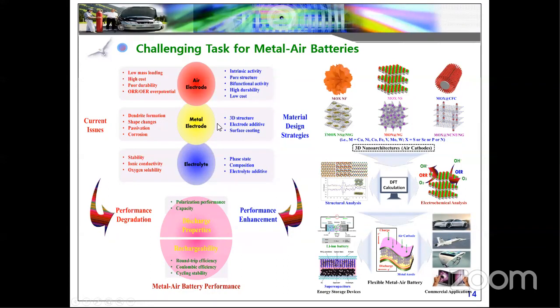The current issue of the metal electrode is dendrite formation; the metals easily form dendrites with the electrolytes. Due to dendrite formation, the shape easily changes or dissolves during long-term durability tests. There are also corrosion effects, because the metal easily corrodes in basic or acidic media. So to avoid this, the anode also needs to be developed. And for electrolytes, we can develop different types. For example, with liquid-based electrolytes, stability is a big issue. That's why we need to avoid liquid-based electrolytes.